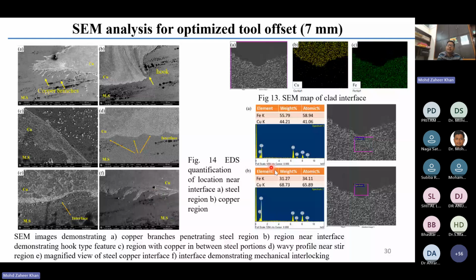Then we did the EDS analysis to see what elements are present, and at the interface you can see that almost equal percentages of copper and iron are present. As we move from the interface to the region slightly on the copper side, the atomic percentage of copper is increasing, and the atomic percent of iron is decreasing.